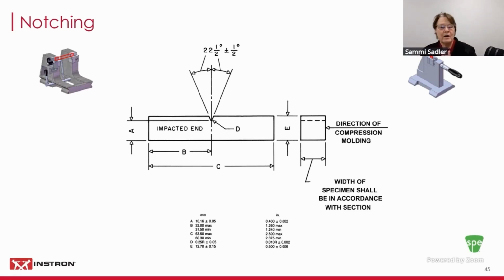Okay, so we get now to the most critical thing that affects test results. The notch. You wouldn't think such a little divot removed from a sample could cause such heartache, but it can. The purpose of the notch is to be a stress concentrator. So basically, when we impact either above or behind the notch, what we're doing is forcing the sample to fail along that notch.